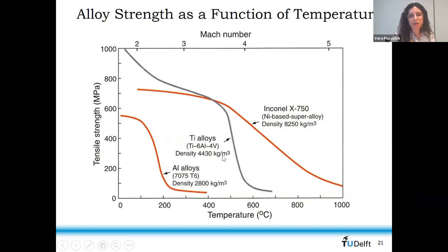The density goes a bit higher, but the advantage of nickel-based super alloys is that this transition in temperature is not as abrupt. Yeah, so the transition in dependence of tensile strength and temperature is for sure better for high temperature applications. It's more predictable. But this is to the sacrifice of weight. So you see that the weight is twice that of titanium alloys, and it's even higher than the aluminium alloys. Yeah, so this is just to give you an example of why this is used.